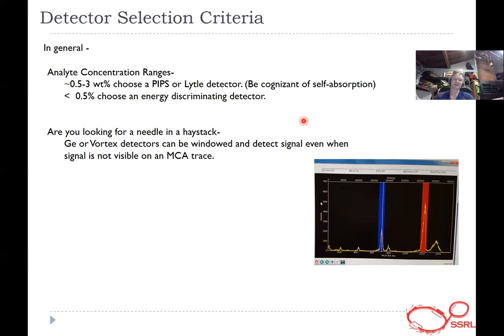Alternatively, if you have a lot of fluorescence, but you want some kind of multi-element sample where they all fluoresce in a similar regime, and you only need to look at a small subset, like if you want to look at manganese in a chromium oxide, above the manganese edge you're going to be fluorescing manganese, but you're also going to be fluorescing a lot of chromium. So a non-energy discriminating detector isn't going to help you a whole lot, because it's going to be flooded by all that chromium fluorescence. But you can window on the manganese region of interest and ignore to a certain degree the chromium fluorescence and get a viable signal from that. And we do that a fair bit.